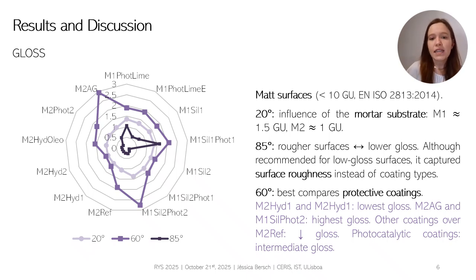What we have seen was that the hydrophobic coatings led to the lowest gloss values, while the anti-graffiti and photocatalytic 2 coating applied to the silicate paint led to the highest values. Almost all coatings applied over mortar type 2 reduced the gloss values of the reference samples. Normally, photocatalytic coatings resulted in intermediate values.